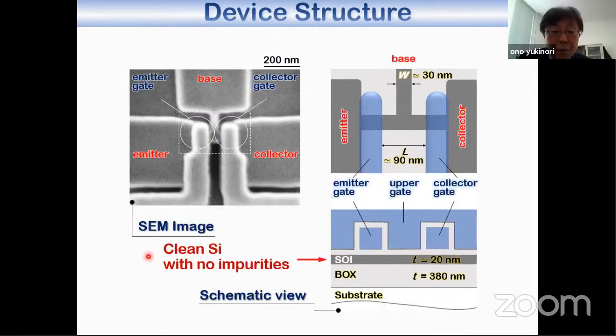One of the important points for the fabrication is that we used a very clean silicon SOI layer with no impurities. This is because in order to observe the hydrodynamic effect, or in order to make the electron-electron scattering effective, the unwanted impurity scattering has to be eliminated. That's why we use the very clean silicon layers.